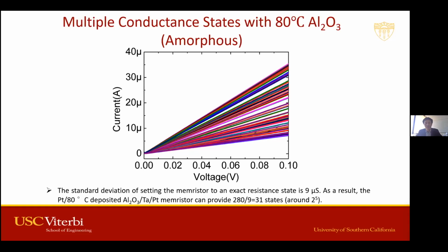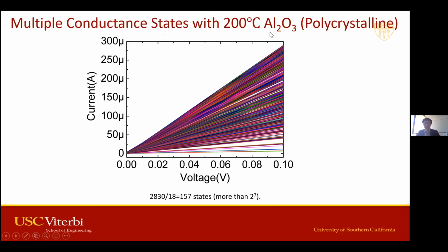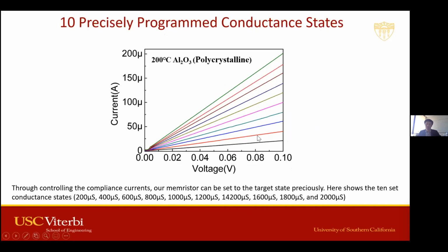So we also want to see whether we can tune those devices into different conduction states. Here is one way you can tune the device to different conduction states: by setting a different compliance current when we switch it on. With the 80-degree deposited aluminum oxide, we can switch to about 31 states. However, the device with aluminum oxide deposited at 200 degrees C can be switched into 157 states. So now we have this nice device that can be tuned to different conduction states.